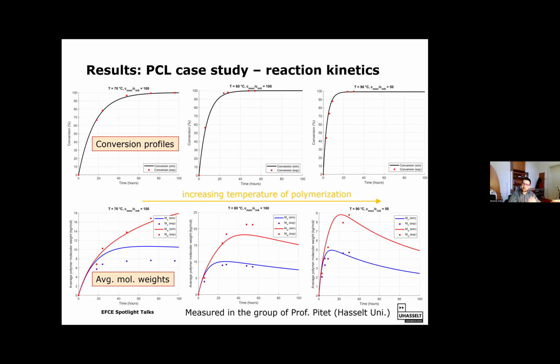Regarding the PCL, or polycaprolactone, the work is still in progress. Here we have an example of 3 experiments that were done at Hasselt University in the research group of Professor Pitet, where in each of the experiments, the conversion of monomer and number and weight average molecular weights are measured. You see experiments carried out at 3 different temperatures, 70, 80, and 90 degrees.